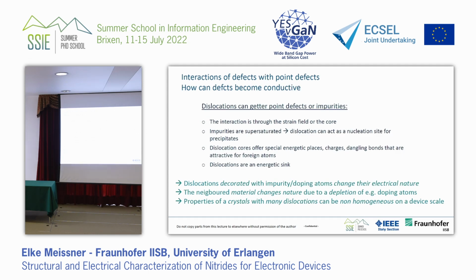And now imagine what happens. The dislocations can be decorated, so they are collecting atoms. Imagine what happens if you have metal atoms in silicon. This is a good example from solar cells. You had metal atoms as an impurity, and you have dislocations or grain boundaries in solar cells. And now, by energetic actions, these atoms go and decorate these dislocations with metal atoms. Then they get conductive. And this is what you don't want, because this is creating leakage current. If you send a current through your semiconductor material, it goes along where it finds the highest conduction path. And this is leakage.